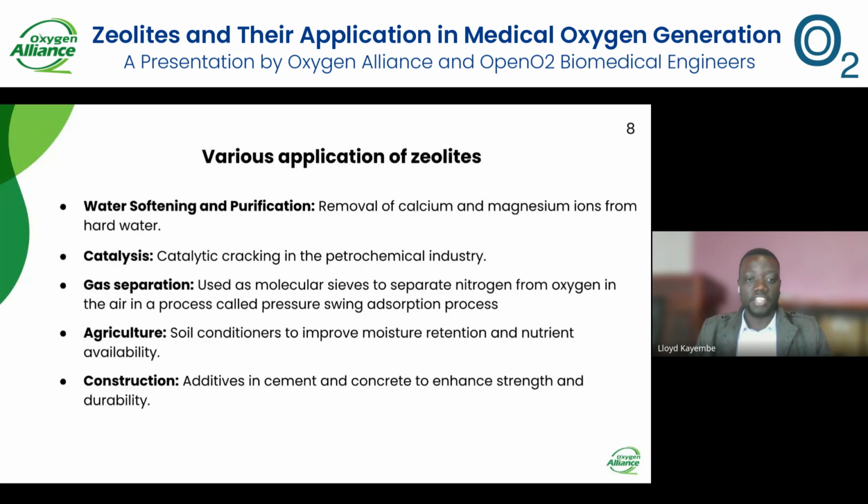This is actually in the medical field, where they are often applied as molecular sieves to separate the nitrogen from the oxygen in the air in a process called pressure swing adsorption. As I've said, this is often due to the properties discussed earlier about their pore sizes, allowing them to selectively trap or absorb certain materials.